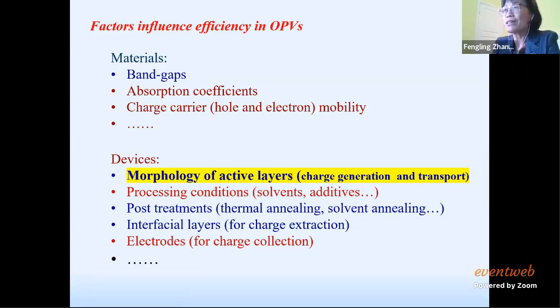For material design, they need to think about the band gap, which should match the solar spectrum to absorb photons from the sun. They also need to think about the absorption coefficient. Larger is better. And finally, one of the most important factors, they should also think about the charge mobility. Because if the charge is generated but not transported efficiently to the collection electrode, there is still a high possibility that it will recombine and be lost.